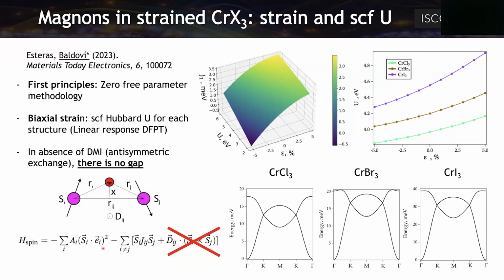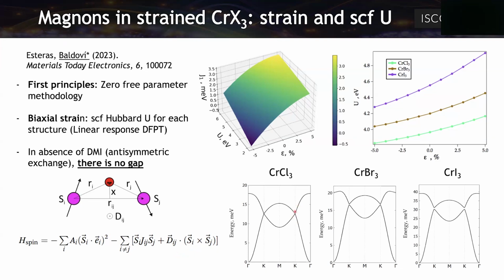So we have the exchange interaction and the magnetic anisotropy. We can add isotropic and anisotropic magnetic exchange interaction, but also add the Dzyaloshinskii-Moriya interaction. When we cancel this interaction, we observe that we have a Dirac cone in the magnon dispersion at K for all three materials. This is normal by symmetry in this material. But when we activate the DMI, we observe that the gap is not open for the chromium chloride 3, it's slightly open for the bromide, but we have a clear gap, fully ab initio, at the K point.